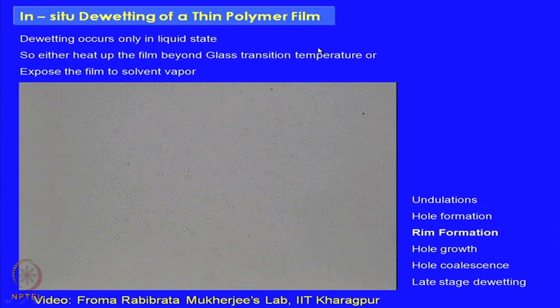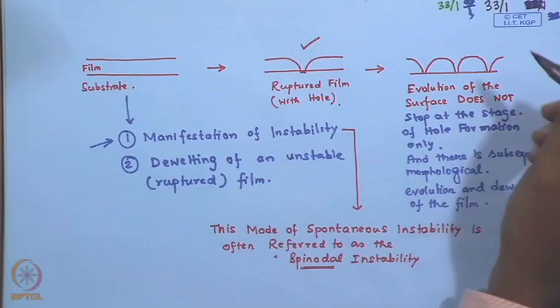So, this is a movie that has been taken in my lab by my research students. What you are seeing is a real-time picture under an optical microscope. The gray color is actually an intact thin film, and you see that there are some holes which have just started to appear. These holes have appeared due to spinodal instability. So, this was a spinodally unstable film. These holes have just started to appear.